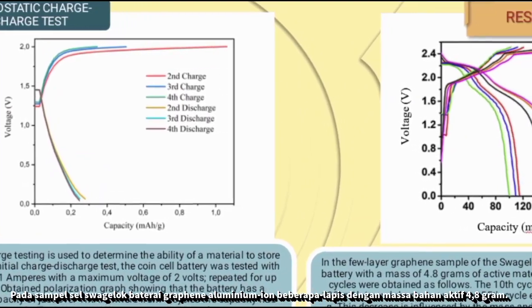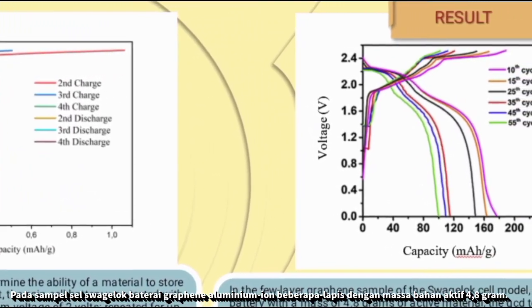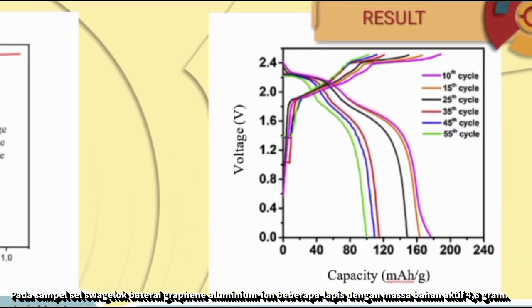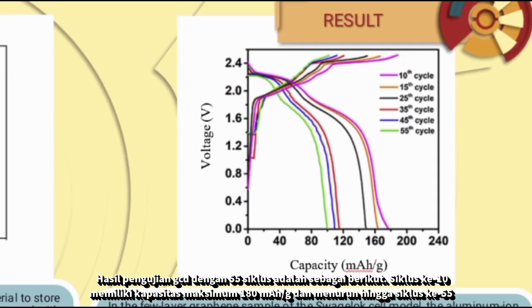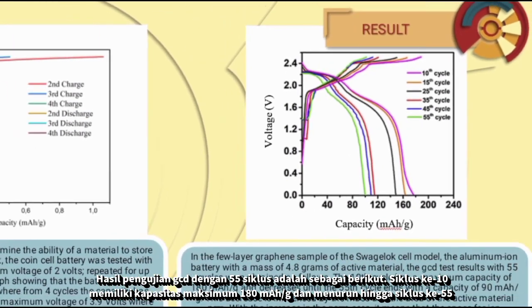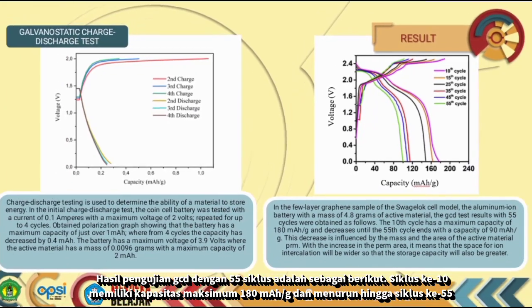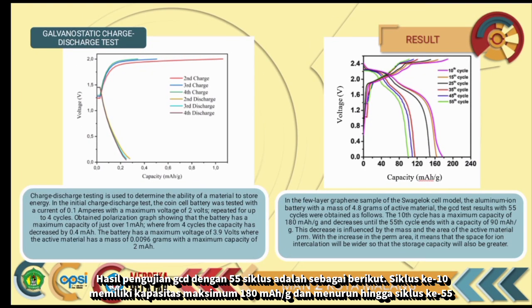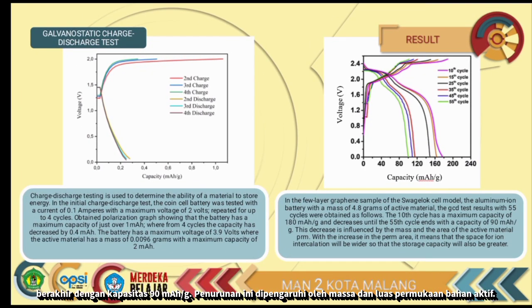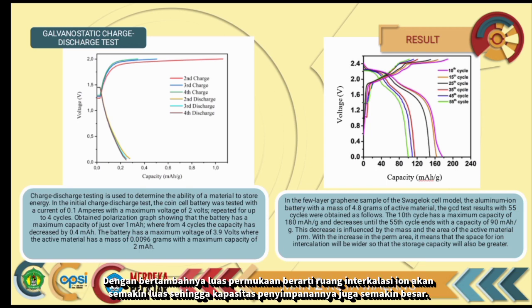In the Swagelok cell sample of a few-layer graphene aluminum ion battery with a mass of 4.8 grams of active material, the results of the charge-discharge test with 55 cycles are as follows. The 10th cycle has a maximum capacity of 180 mAh per gram and decreases until the 55th cycle ends with a capacity of 90 mAh per gram. This decrease is influenced by the mass and surface area of the active material. With an increase in the surface area, it means that the intercalation space for ions will be wider, so that the storage capacity is also greater.